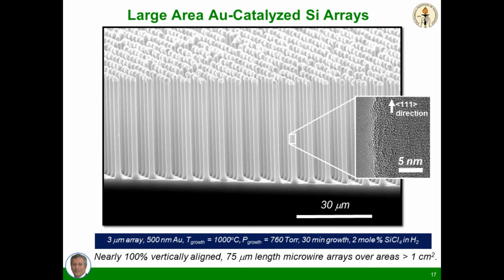Now, when we did this, not only was it interesting, but this problem was only starting, because nobody in their right mind would expect these beautiful single crystals of silicon microwires, which have been optimized in their spacing to reflect as little light as possible and scatter it internally, to be contaminated by gold, which was in the growth process. And gold-contaminated silicon has a very low lifetime, so that the excited carriers can't move 200 microns, they can only move one or two.